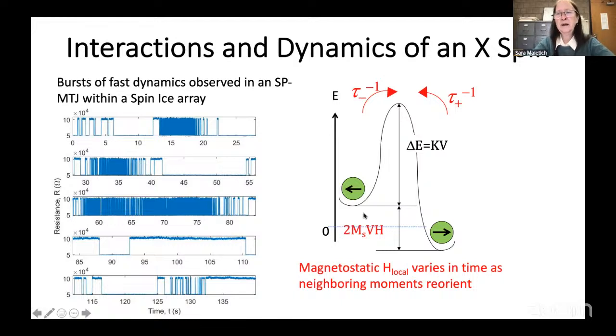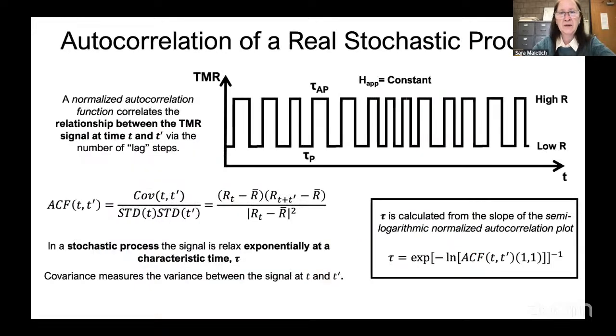And the way that we think about this is to go back to the simple picture of a single particle going over a barrier and coming back. It's stabilized in one state or another, parallel or anti-parallel, by a Zeeman field. Usually, this is due to an external applied field, but in the spin ice, this is changing when the neighbor spins, the neighbor MTJs, are reversing their magnetic direction. So this magnitude gets bigger or smaller. You can trap in one state, or you can destabilize it so it gets over the barrier faster. And this is what we think is happening over time with the X devices.